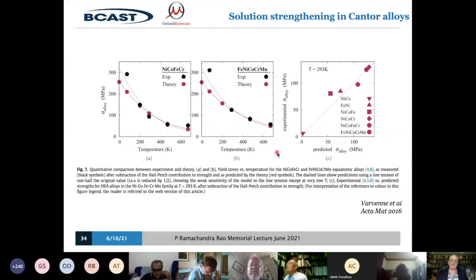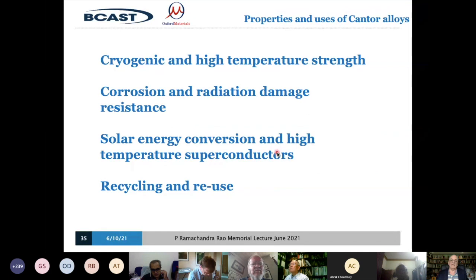So as a consequence, what are the uses of Cantor alloys and other high entropy multi-component alloys being pursued? Well, already Cantor alloys have the best low temperature mechanical properties. They're being looked at for cryogenic purposes. They also have outstanding high temperature properties, and they're very thermally resistant. But the BCC refractory alloys are even better, and they're being looked at very strongly.